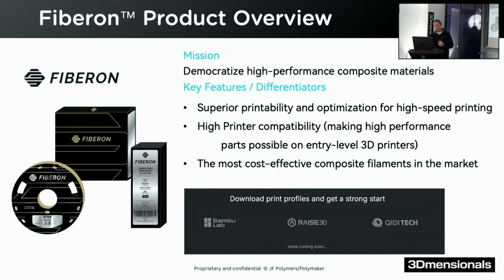But we have a larger core, and that's because the carbon fiber filaments are much stiffer by nature. So if we wrap them around a smaller core, then it's a bit like a spring, so it's harder to unspool, and also the filament can tend to snap. So this is our standard size. It's a 500 gram. And then we also introduced a 3 kilo spool that you can just see over here.